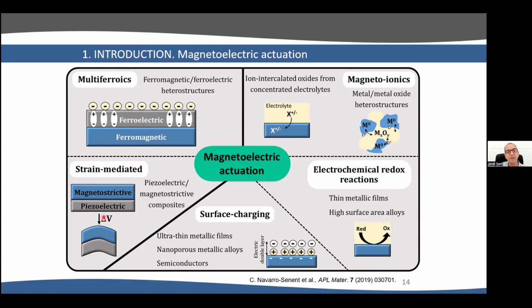There are other mechanisms to control magnetism with voltage besides these two, for example, surface charging. If you have an ultra-thin metallic film or a semiconductor and you accumulate electrostatic charges, then these charges can modify the electronic band structure, eventually leading to changes in the magnetic properties, anisotropy, coercivity, and so on. But we can move a bit further. We can think of electrochemical reactions. This is quite simple. For example, if you imagine an iron foil that you immerse in water and you apply voltage, the iron will get oxidized, and of course this oxidation will change the magnetic properties of iron.